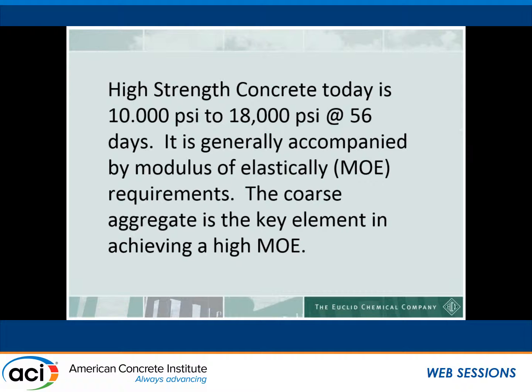High-strength concrete today is 10,000 PSI to 18,000 PSI at 56 days, and is generally accompanied with a modulus of elasticity requirement by the engineers. In the projects that Bill has been involved with in New York City, there's always a modulus of elasticity requirement. The coarse aggregate is the key element in achieving high modulus of elasticity.